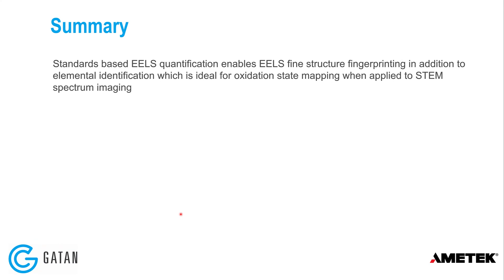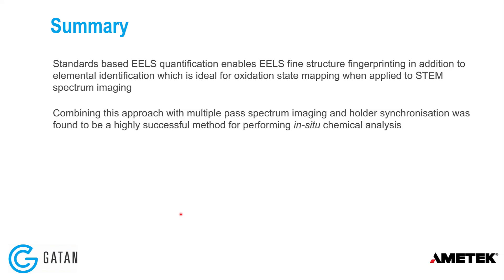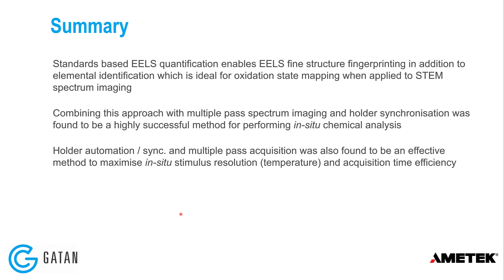In summary, standards-based EELS quantification enables EELS fine structure fingerprinting in addition to elemental identification, which is ideal for oxidation state mapping when applied to STEM spectrum imaging. Combining this approach with multiple-pass spectrum imaging and holder synchronization was found to be a highly successful method for performing in-situ chemical analysis. Holder automation and synchronization with multiple-pass acquisition maximized in-situ stimulus resolution while maintaining good acquisition time efficiency.